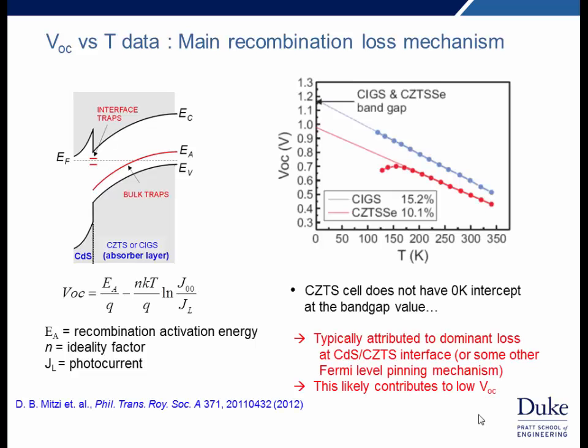And comparing CIGS with CZTS, in the case of CIGS, if we extrapolate VOC to low temperature, we get the band gap of our CIGS absorber. And this is what's expected in a well-behaved thin film device.